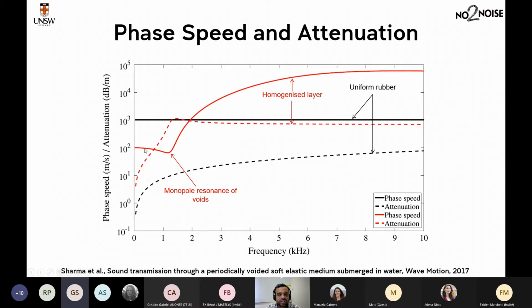right? Whereas here, for the effective medium which is made by homogenization of cavities in your soft media, there is a huge change in the sound phase speed and attenuation, especially around monopole resonance. So this is where the monopole resonance occurs. So here the sound speed isn't going negative, but you can have certain parameters with which you will see that the sound speed can go negative. It is possible. For this case, it is safe to have a quasi-static approximation for density. It is safe to assume that the density does not change with frequency, right? But when you have cavities in soft media, the bulk modulus and therefore the phase speed and attenuation change with frequency.